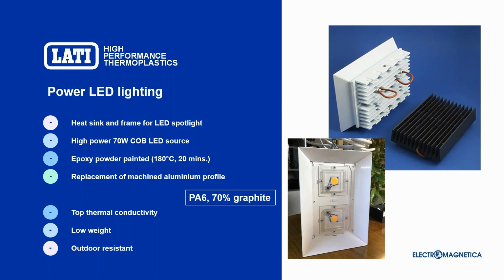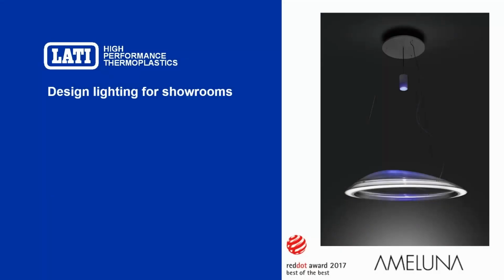As Federico explained, graphite-filled materials are also electrically conductive, and this allowed epoxy powder painting and also the following curing process. The component is significantly lighter compared to the original one, and also it works outdoors, so it's outdoor resistant.